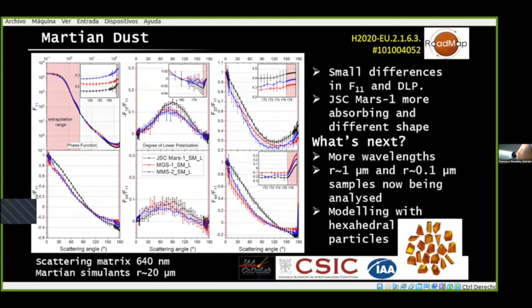For the small sizes, we are planning to measure the scattering matrix. This is the scattering matrix of the larger sample, but we also have a sample centered around 1 micron and one centered about 0.1 microns. These are the ones that are actually relevant for Mars. And our plan is to measure the scattering matrices and give them to the modelers and to the people who work in retrieval, to do a better job in retrievals.